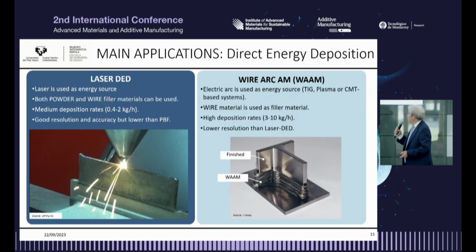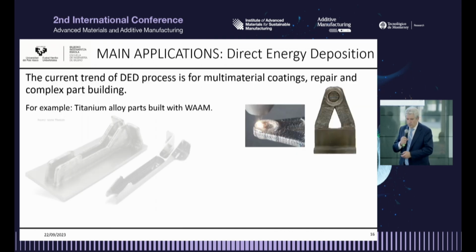So going to the second group of processes, the direct energy deposition. In that case, we use a laser or an electric arc to deposit material. The deposition rate is much higher, but the resolution and the precision are lower. Mainly these techniques are used for repair, for coating, and even to make bigger parts. And I will show you now an example.